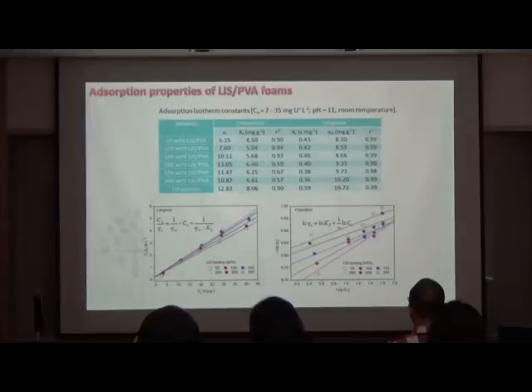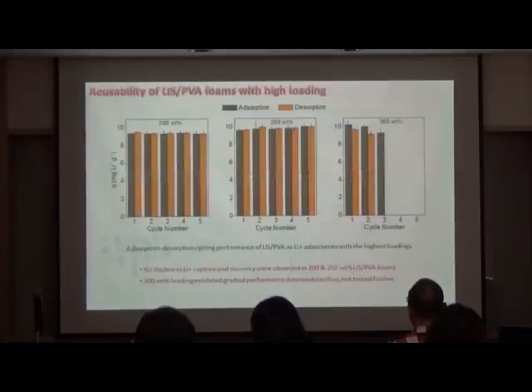To determine the maximum capacities of the foams and to elucidate their adsorption behaviors, the widely used Langmuir and Freundlich models were employed. Calculated isotherm constants are shown here in this table. It reveals that the lithium uptake of the LIS in composite foams is better characterized by the monolayer Langmuir-type adsorption than the Freundlich. Now, this result is consistent with those reported by previous studies, and also verifies the chemisorption of the lithium ions by the LIS concomitant with the release of H+ into the solution.